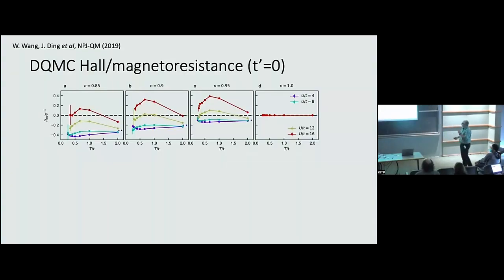Okay, so just very, very quickly, there are different ways to evaluate the Hall response, either in a way of looking at a 3-current correlator, or a way from Asa-Auerbach, or actually just including the magnetic field. So we've used all three. This is the Hall coefficient as a function of temperature for 4 different values of U. Of course, at half filling there's no T prime, so it's particle symmetric. So there's nothing here, of course.